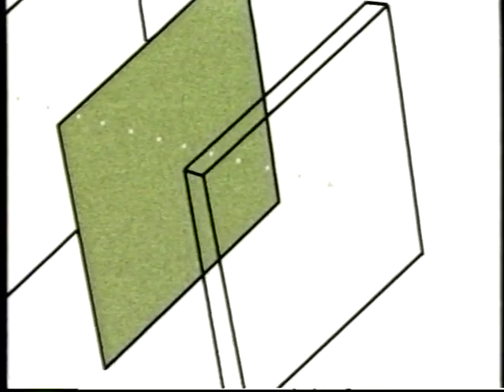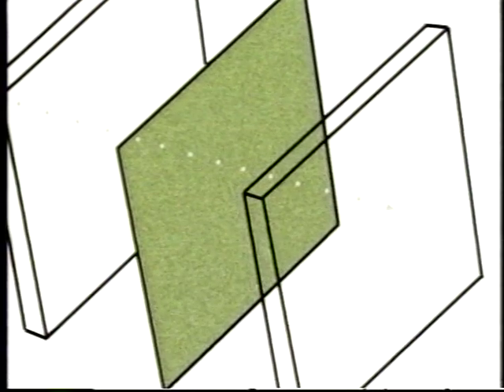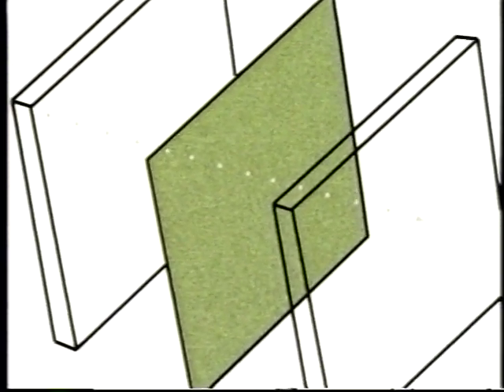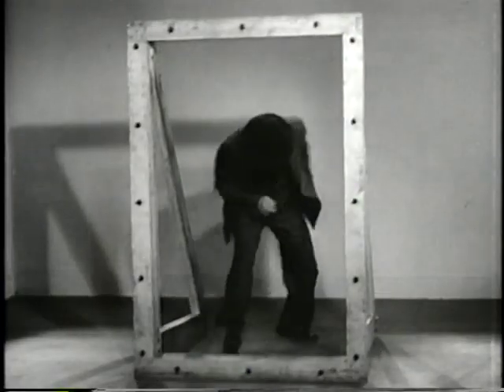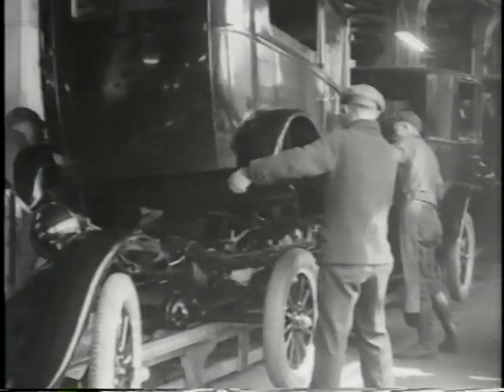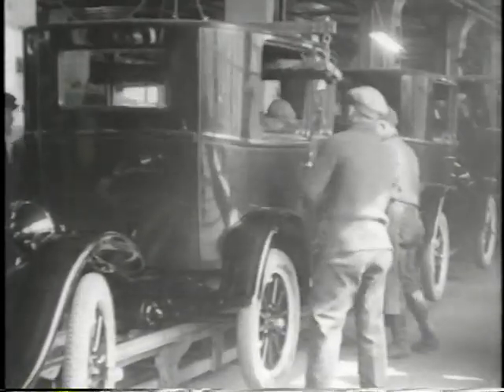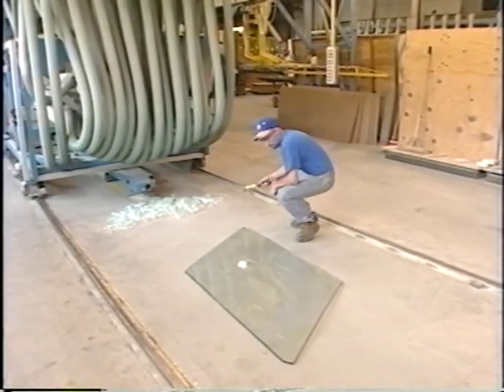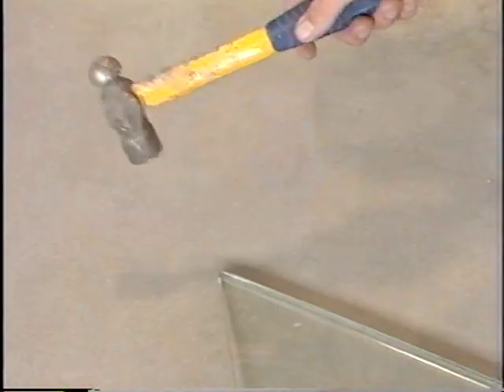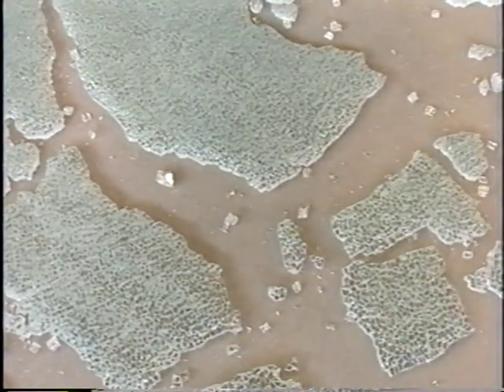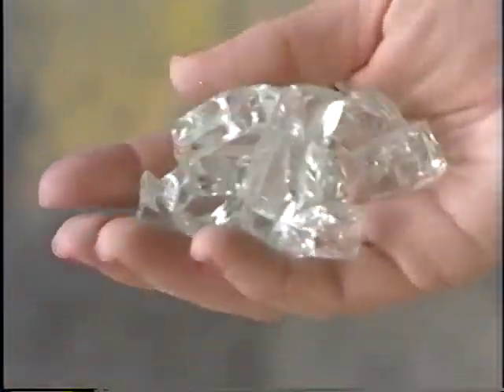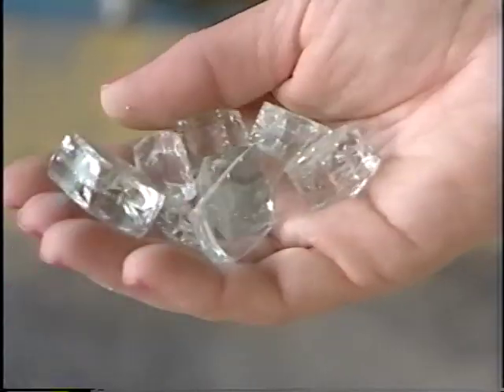In 1903, Frenchman Edouard Benedictus invented laminated glass, which was 2 layers of glass held together with a cellulose inner layer. When the glass broke, the pieces were held in place by the cellulose lining. By 1919, Henry Ford was using laminate in the windshields of his cars to make them safer. A decade later came the next advance, tempering. A heating and cooling process that hardens glass and allows it to break into rounded chunks rather than dangerous shards.